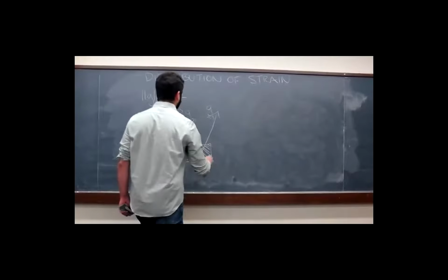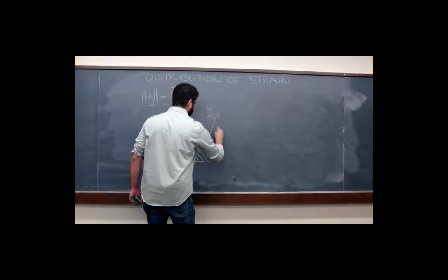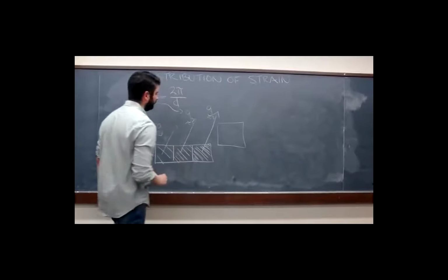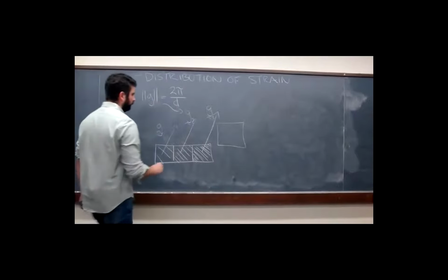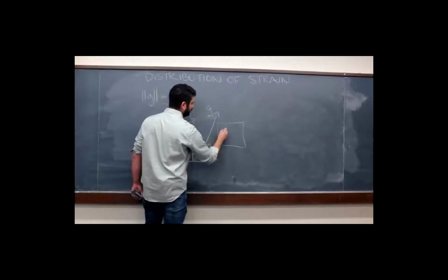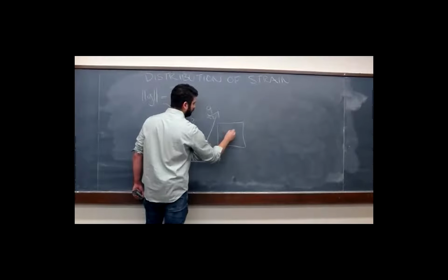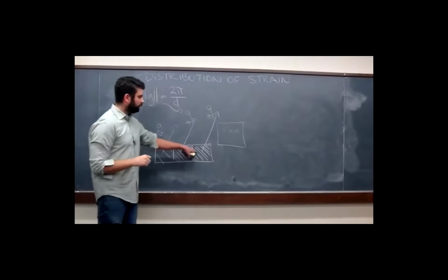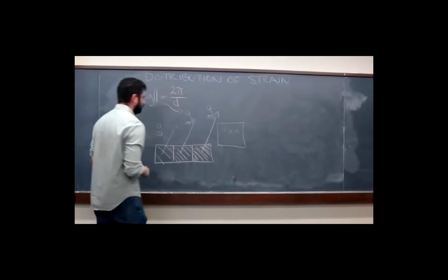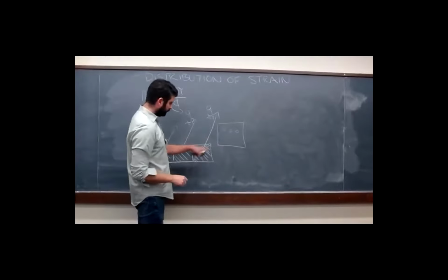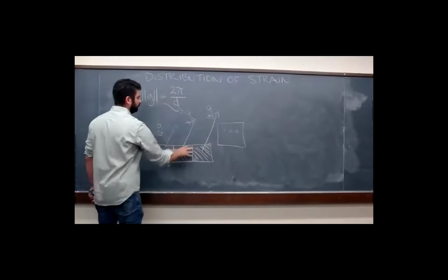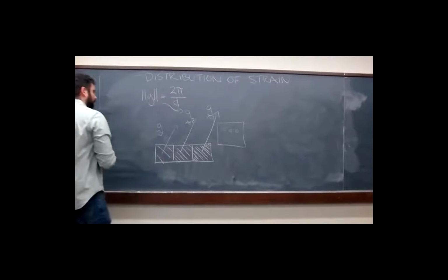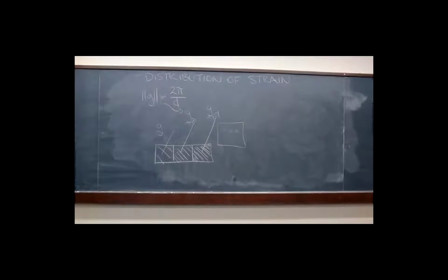So what happens if we stick the detector in really close? So our case where D is small. What actually happens is the diffracted intensity from the 3 crystallites is going to be dominated by their positions. So we've got the 3 crystallites spaced out, and we're getting intensity from the 3 crystallites on the detector.